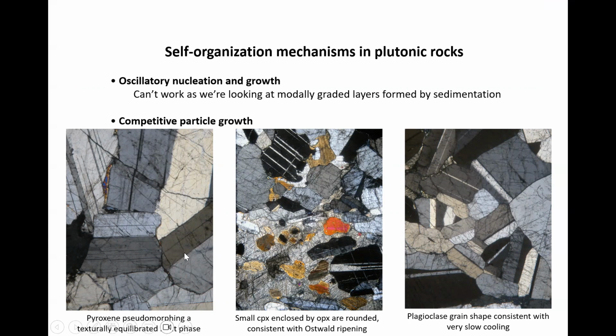First, there's abundant evidence for slow cooling. Plagioclase grain shape is linked to cooling rate. The lower the aspect ratio of the plagioclase, the slower it grew. And we can clearly see that the plagioclase is almost equant in these rocks. Secondly, where there is no second phase in the pure plagioclase regions, we've got a beautiful granular microstructure, which is very, very slow cooling in the subsolidus. So it effectively becomes like a metamorphic rock. And you can see that very, very beautifully here.